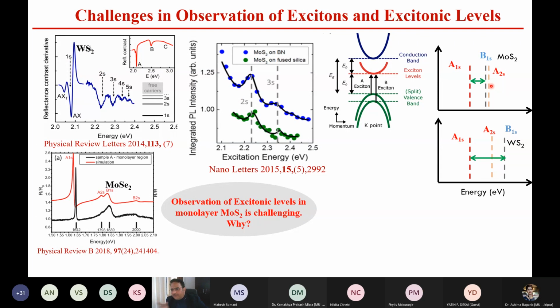So which means the gap between the excited states is very small, as well as this B exciton, which is coming because, you know, the valence band actually splits up because of the spin orbit coupling of the molybdenum. Tungsten, being a higher atomic number element, has a larger spin orbit coupling there. So you are able to distinguish between these two energy levels. But in the case of MoS2, since it has a very small spin orbit coupling gap here.